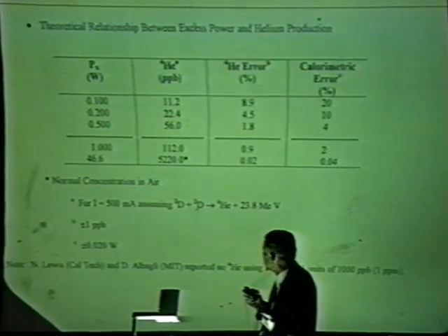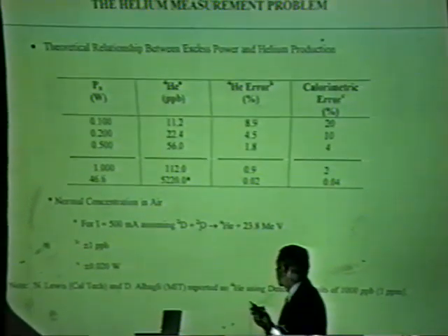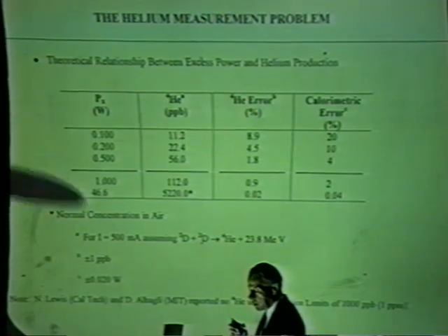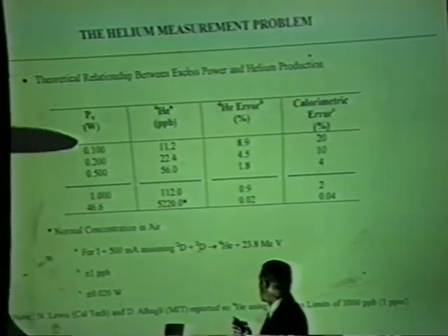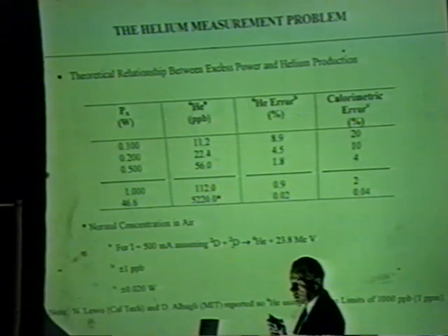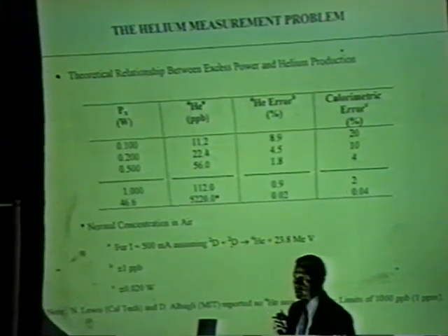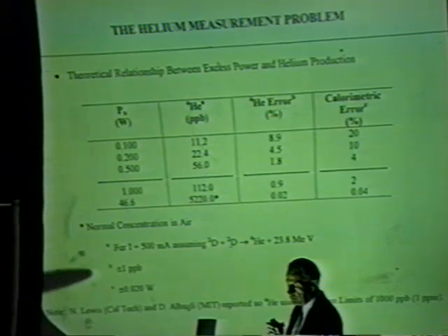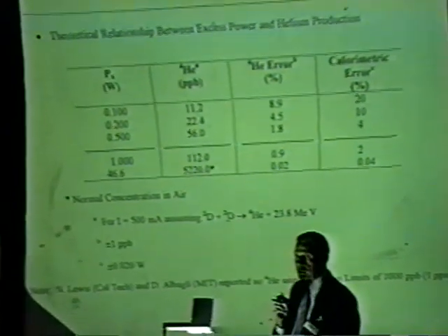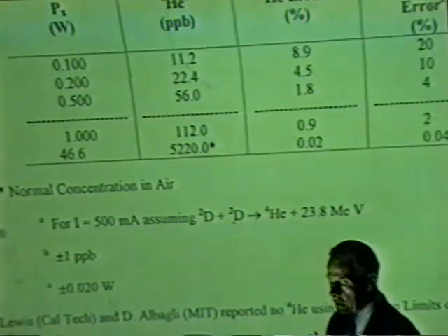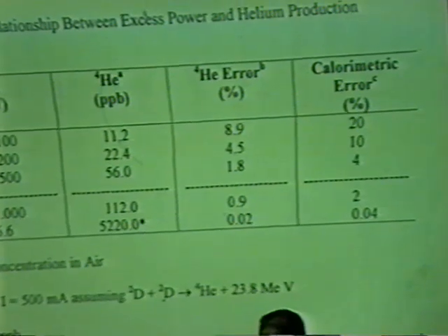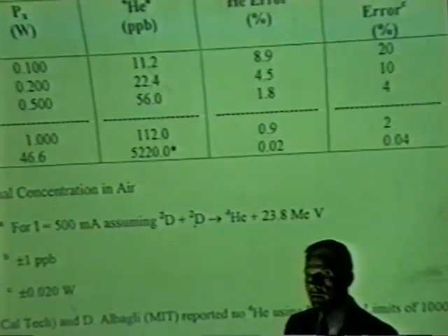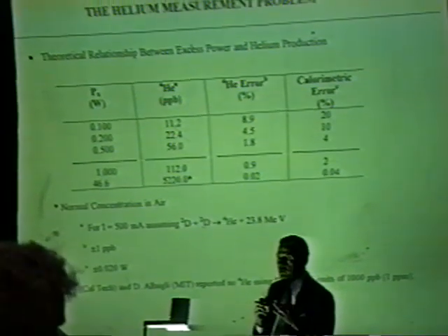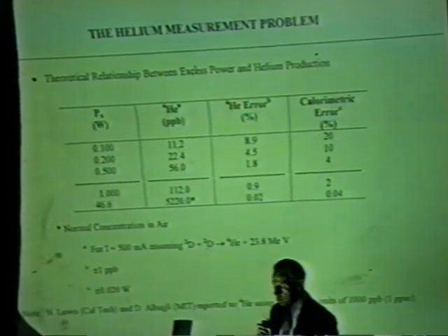This summarizes the major problem with helium analysis if you're doing electrolysis. This first column shows the excess power that, suppose, you measure and how much helium you would expect in your gas sample if we assume it's the DD fusion going to helium-4 and 23.8 MeV. Also using 500 milliamps, which is very typical current that we use in these studies. It varies a little bit if you use a different current. Higher current will dilute it somewhat, lower current will make it a little more concentrated.